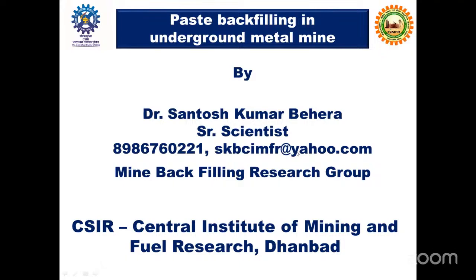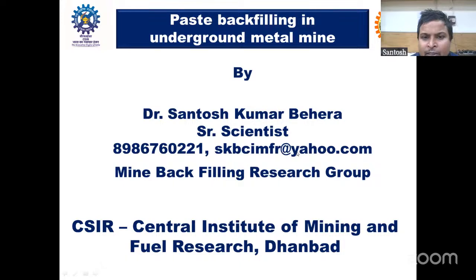Particularly in paste fill, as I was telling you, the separation of water from the backfill mass has to be minimum, up to 5% only. We are adding 20 to 25% water to the underground stope. Studies have found that 12 to 15% of that water is used for cement hydration, because the volume of the backfill is very high. Imagine a stope of height 50 meters, width 30 to 50 meters, and length 20 to 30 meters.